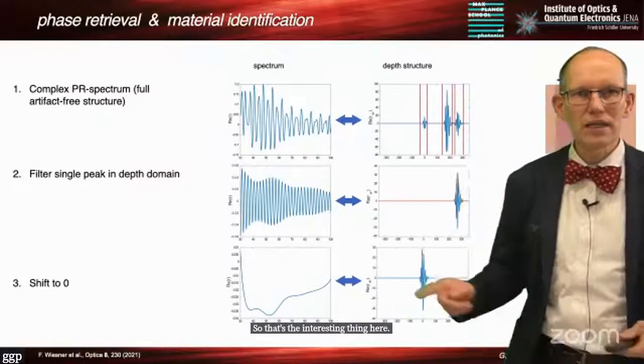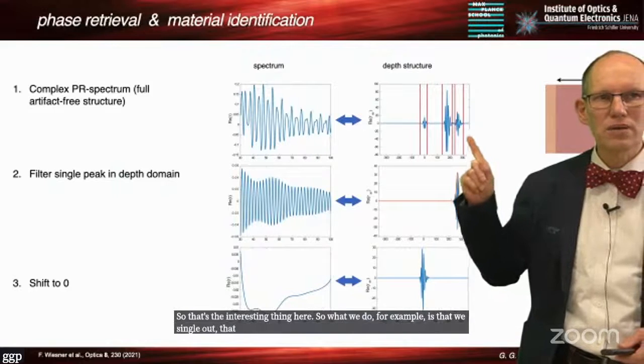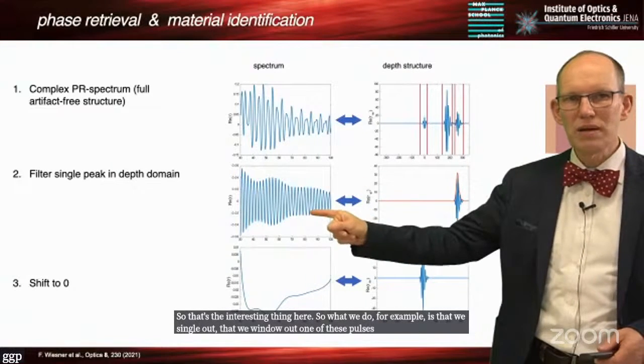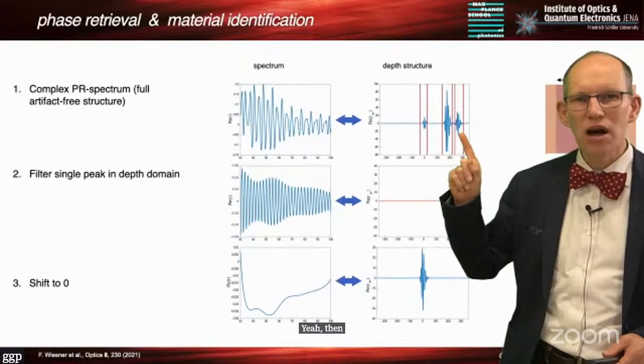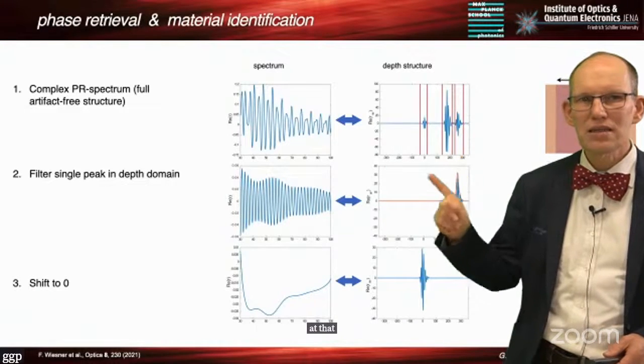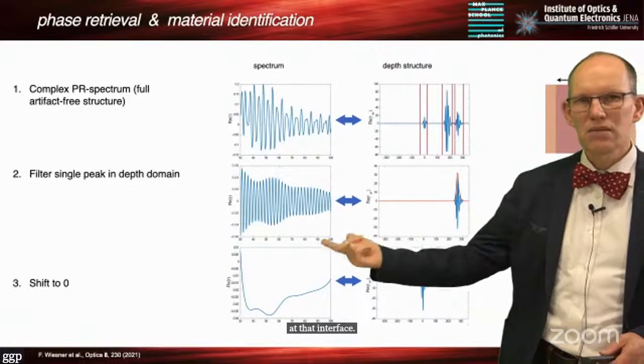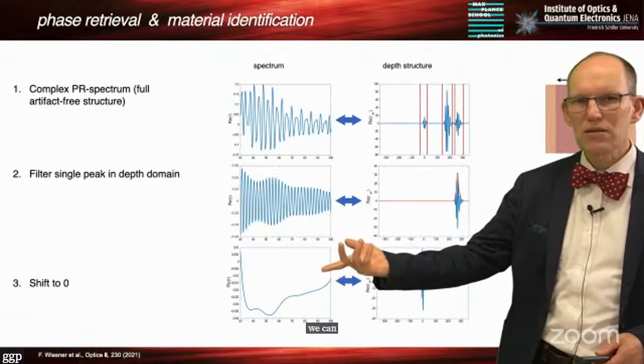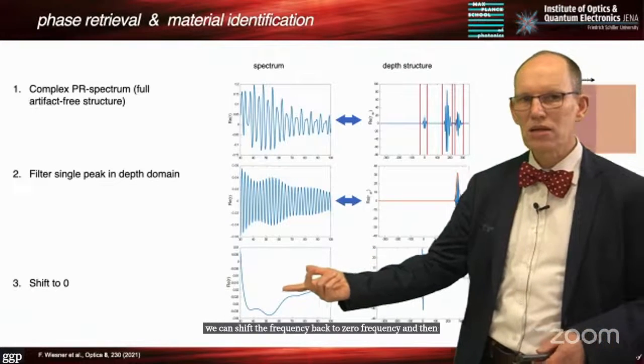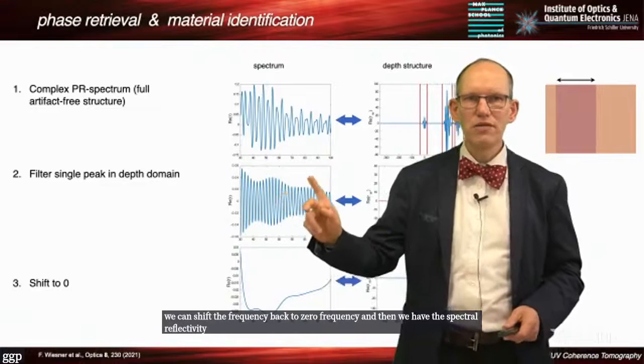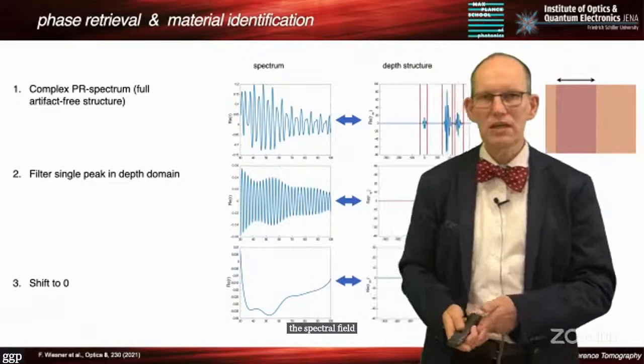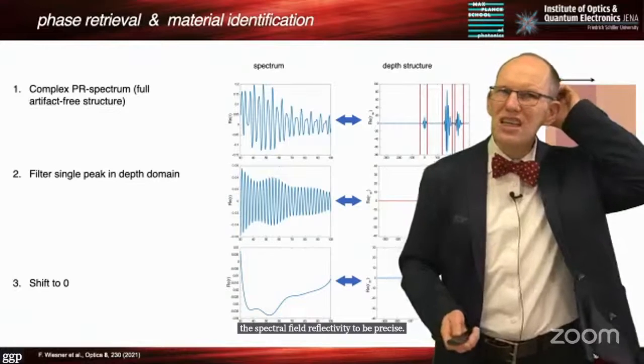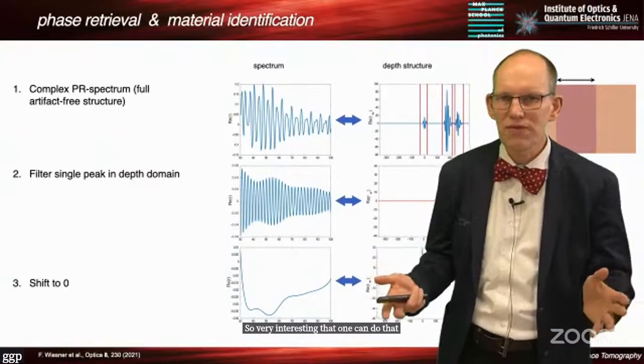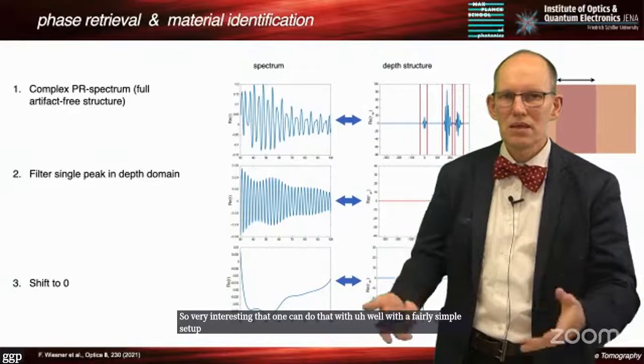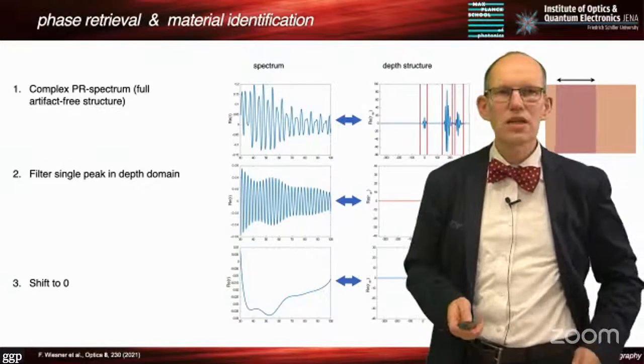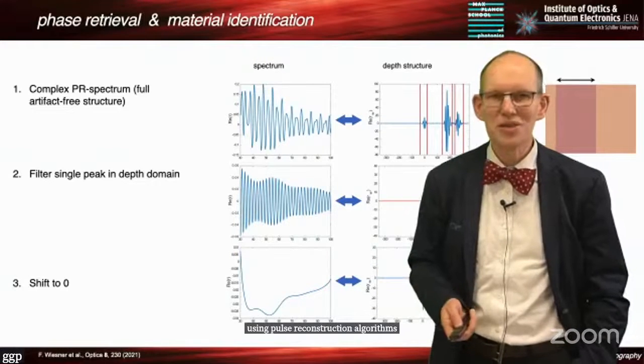So what we do, for example, is that we window out one of these pulses and Fourier transform it back. Then we have the reflection only at that interface, right? We can shift the frequency back to zero frequency, and then we have the spectral reflectivity, the spectral field reflectivity, to be precise. Yes? So it's very interesting that one can do that with a fairly simple setup, using pulse reconstruction algorithms and high harmonics, of course.